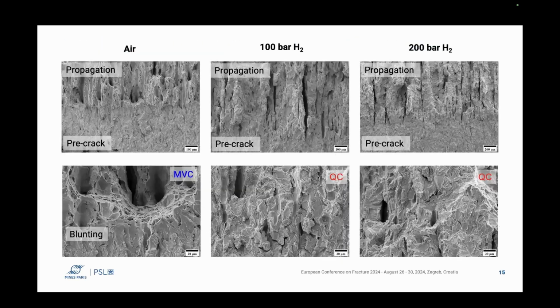And we can see this in the fracture surface. We need higher magnification to see the blunting here. And we cannot see the blunting at 100 bar and 200 bar. At the beginning of the propagation, we see all quasi cleavage fracture. And we can also see these veins that are related to the inclusions of this material.